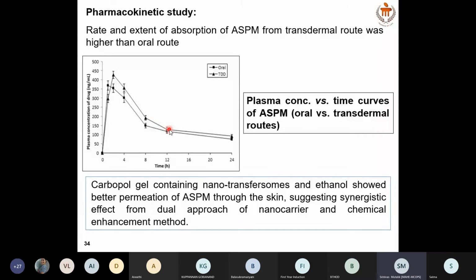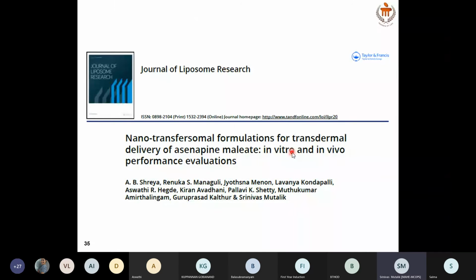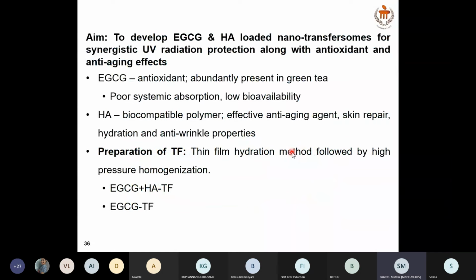in presence of transferosomes. So finally, carbopol gel containing nanotransferosomes and ethanol showed better permeation of asenapine maleate through the skin, suggesting synergistic effect from dual approach of nanocarrier and chemical enhancement method. So this was published in a journal.